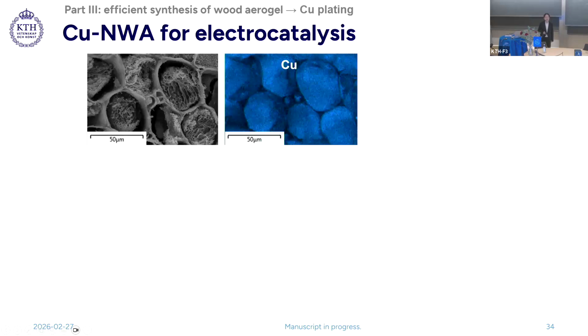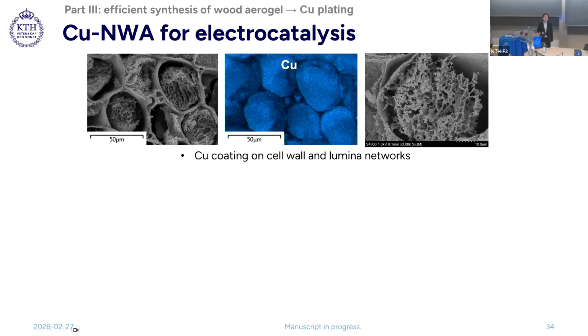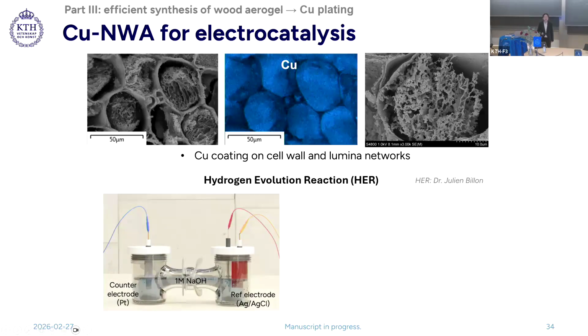EDX mapping shows the wide presence of copper, especially in the lumen space. Zoomed-in SEM images reveal that in addition to the cell wall, the lumina networks are densely coated with copper particles, also confirming the effective utilization of lumen. Hydrogen evolution reaction was then evaluated due to the electrical conductivity of copper and its catalytic performance. Here, the copper-plated aerogel acts as a working electrode for water splitting.